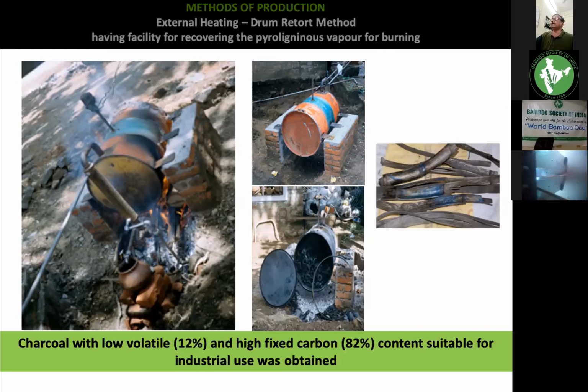What we observed is that we connected a pyrometer and recorded the temperature. When we produce at low temperature, as mentioned earlier, we get a product with a little higher volatile content, and the yield will be a little bit high. And when we produce at higher temperature, we get a product with lower volatile content and higher fixed carbon content. So we have the option of whether we want charcoal for domestic purpose or for industrial purpose. And another observation we got is, we can go to the next one.